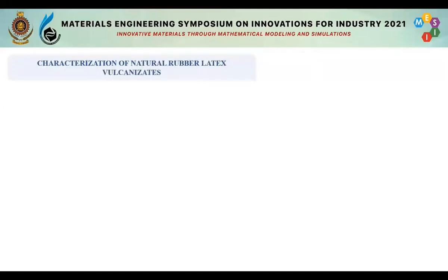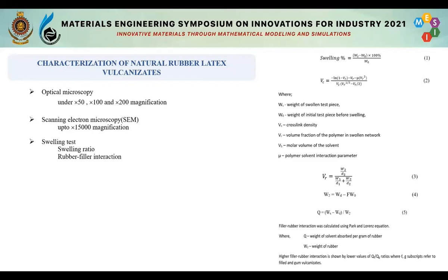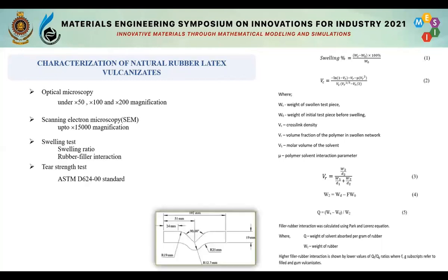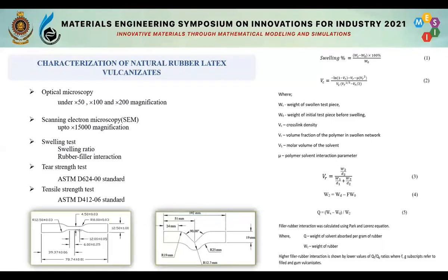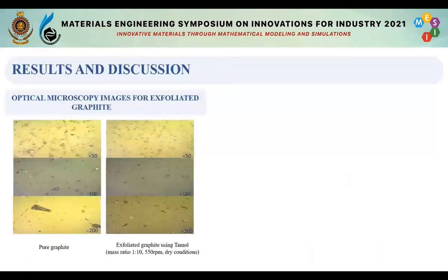Several different characterization techniques were used to characterize the natural rubber latex vulcanizates. First was optical microscopy, then scanning electron microscopy, and the swelling test was done. This is a conventional testing method used in rubber-related processes. Using this testing method, we can calculate swelling ratio and rubber filler interaction, get the cross-link density of rubber vulcanizates, as well as the interaction between rubber and the fillers added. Next, the tear strength test was done under ASTM D624 standard, and then the tensile strength test was conducted under ASTM D412 standard.